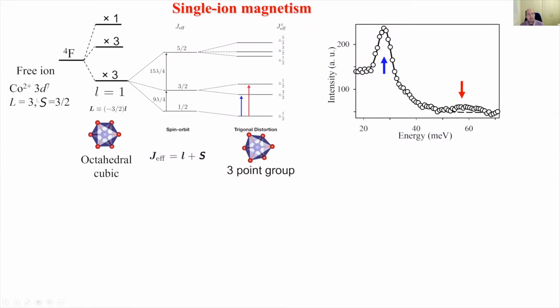So for that, let's consider the ground state of cobalt 2+ ion. So here we have 7 electrons. And for free ions, this would correspond to L equals 3 and spin 3/2. Now, in an octahedral cubic environment, the 7-fold orbital degeneracy is split into a lower triplet and some other states, triplet and singlet hierarchy. But this lower triplet is equivalent to an effective L equals 1, and via spin-orbit coupling, this gives rise to this energy diagram here, where the ground state is J effective 1/2.